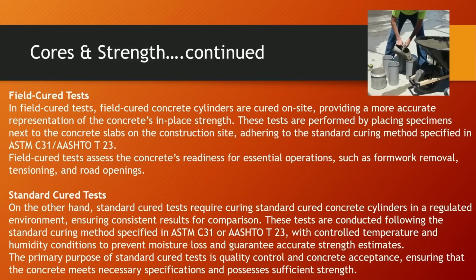All that really means is they got a box and they put their cure box like right outside of your trailer, right by the steps, someplace where it's not going to get disturbed. To me, it just makes sense that you would want the samples cured just like the slabs curing, right? But a lot of times they're just standard cure tests. Standard cure tests require curing the concrete cylinders in a regulated environment, ensuring consistent results for comparison. These tests are conducted following the standard curing method specified in ASTM C31 with controlled temperatures and humidity conditions to prevent moisture loss, guaranteeing accurate strength estimates.